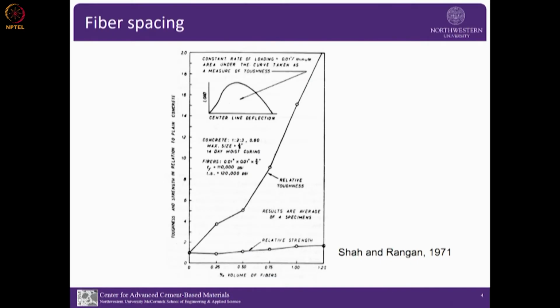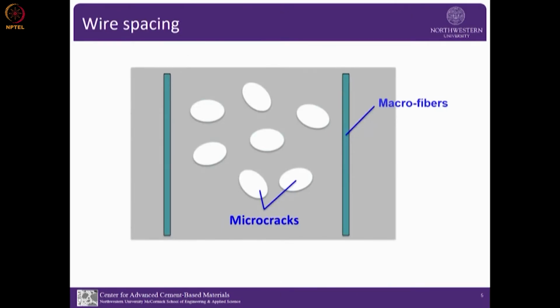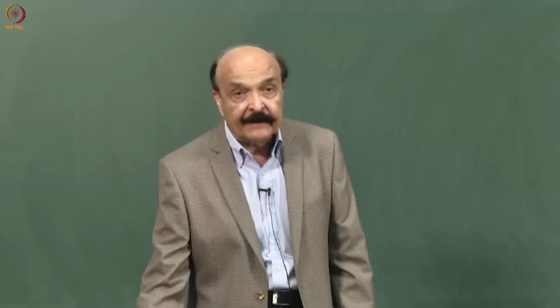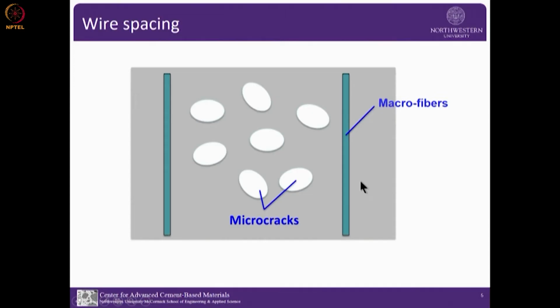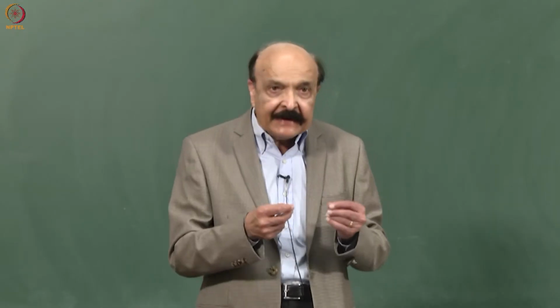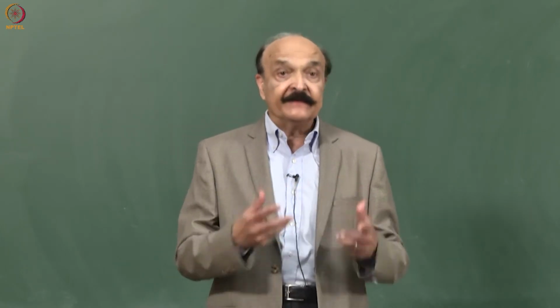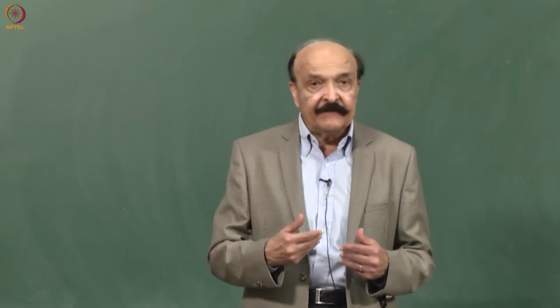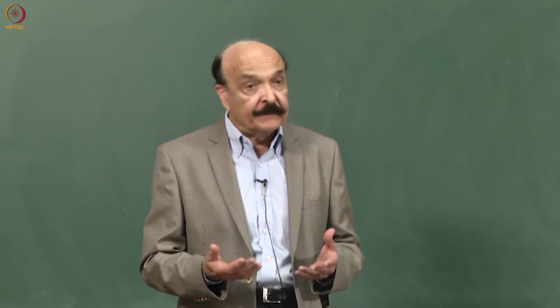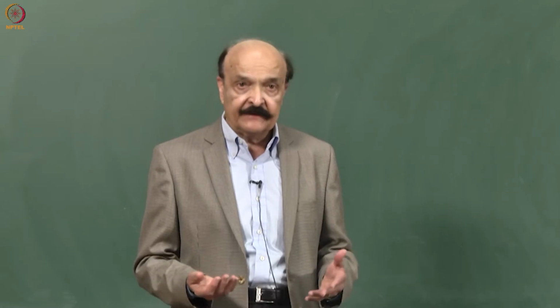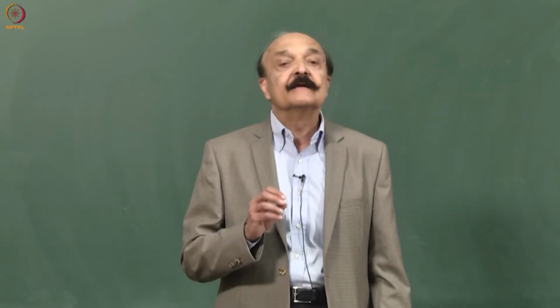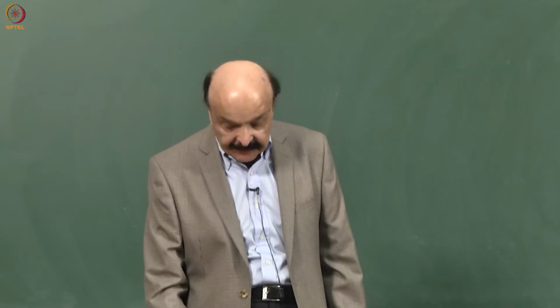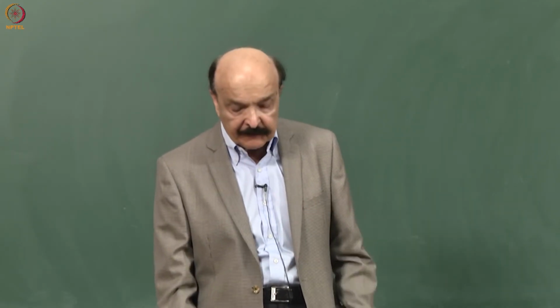And in fact, why is that? One of the reasons there is no effect of spacing is that at the meso scale, the cracks start at the micro level. These fibers are macro fibers in the millimeter range, and we are talking about 1% more or less. So before the fibers can interact with the crack, microcracks have already coalesced into a macro crack. So tensile strength is already formed. Then they will constrain crack opening or crack width, and toughness. That is really the basic idea about the currently used fiber reinforced concrete.